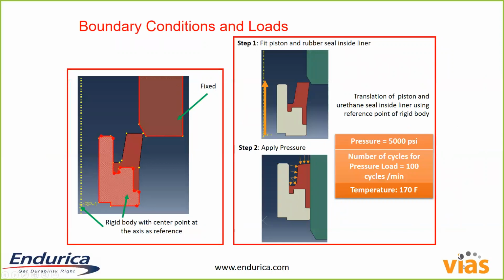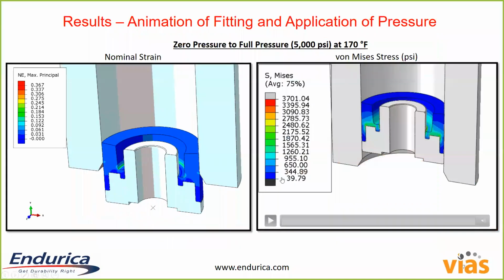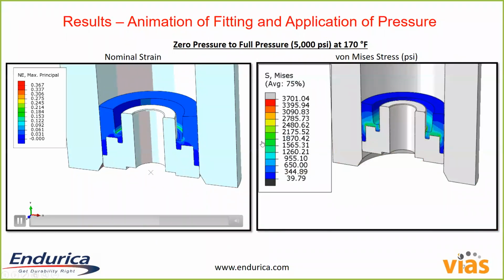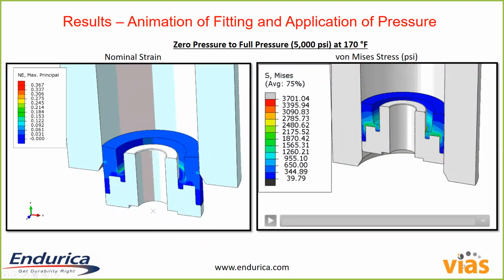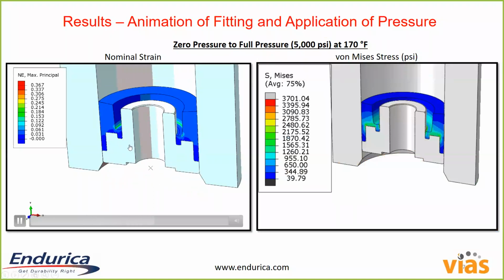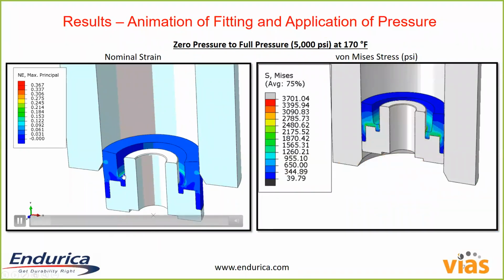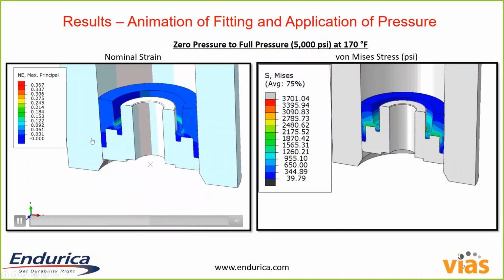This is a slide that summarizes the boundary conditions on the model. First of all, step 1 is fit the piston inside the liner. The operating pressure is 5,000 psi, and the question is how many cycles of that 5,000 psi does it take, and where is it going to start cracking? How many repeats of the 5,000 psi load is it going to take at 170 F? And again, just these animations. These animations are showing the strains and the stresses that are developing on the part. Where you have corners in the model, you're getting strain concentrations. So that's the insertion step.